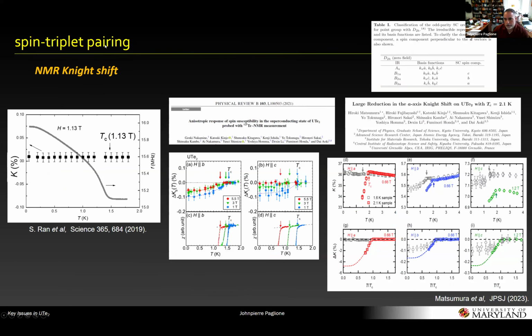So NMR has been an evolving story. I think I counted recently, there are probably 10 or 12 papers, mostly by the same group. Starting from our own work in collaboration with Iowa State, with Furukawa's group, showing that there was no discernible Knight shift change through TC. And just to dispel any worries about the strontium ruthenate saga, this is the in situ measurement showing the frequency change at TC, so there's no heating here.